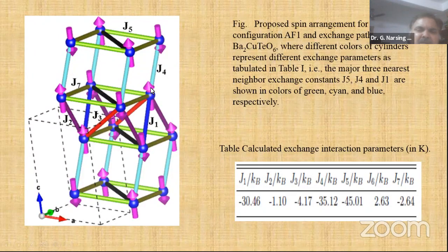But here the beauty is that there are 3 major contributions, J1, J4, J5. We have many exchange interactions, and how can we calculate J1, J4, J5? This depends on the distance between two spins. If the distance between them is small, the interaction strength will be more. J1 and J2 have almost similar distance, but J2, as they calculated, is not exactly what we get as a combination of these. So only J1, J4 and J5 are acting, with more energy, which means these interactions are strong.